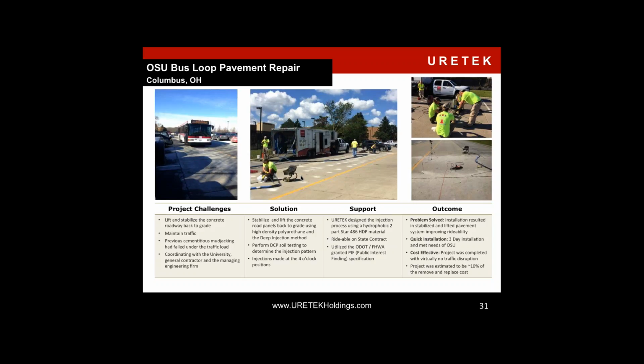There were previous repair attempts made. They used cementitious grout to mudjack and bring it back up. However, that was short-lived. As I mentioned before, under vibratory loads, cementitious grout will fail and break apart, as is the case here. So we were able to bring this back up over 3 days, did a significant part of it, and hence also having that excellent load transfer from panel to panel. So this is where the buses run constantly. So we're able to bring that back up and have a successful repair for them.